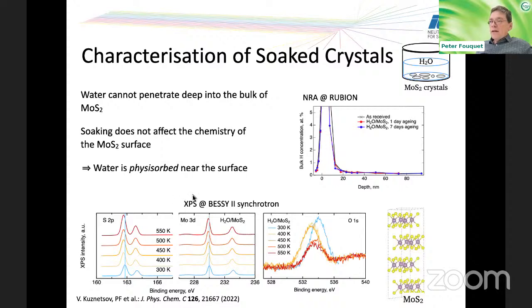And also when you look at XPS, and then heat up the sample, look at the sulfur line, at the molybdenum lines, oxygen line here for comparison, there's not much happening basically. So no chemistry happening. The water is only physisorbed on the surface.